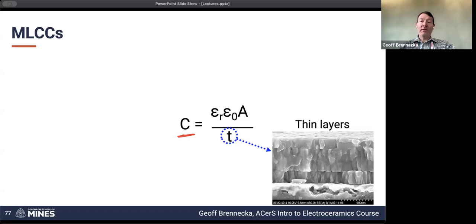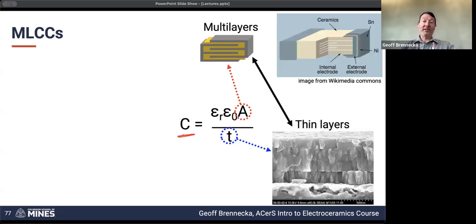I showed you the picture at the very beginning that is 80 microns thick across hundreds of layers. So now we're talking tens to a small number of hundreds of nanometers of dielectric layer each, and do that reliably. It's a big challenge. You can also increase the effective area of the capacitor by just stacking things into a multi-layer sort of buildup. So the overlapping area here between each of those electrode layers gives us the effective area where we're able to store charge. So in this region, that's where the fields will drop, and that's where the energy will be stored. So these regions at the edge are just passive.